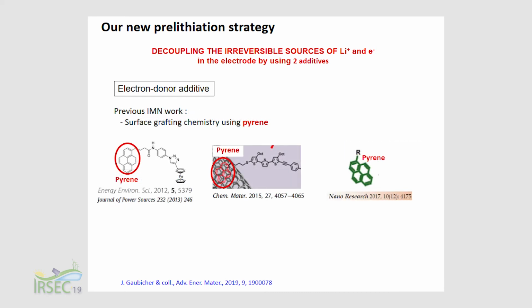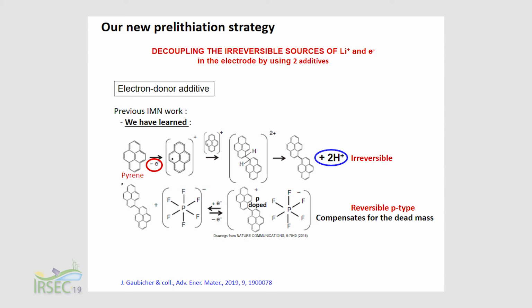So in fact, in our previous work in our lab, a few years ago, we have used pyrene-based molecules to do some surface grafting modification of some materials. And here I show two examples of molecules we have developed. And these works have been published in 4 papers from 2012 to 2017. And from this work, we have learned the following. We have learned that the electropolymerization of the pyrene molecule, of course, provides some electrons irreversibly. This is what we want. And we obtain this kind of oligomer, which can be oxidized with the second reaction shown here, which is a p-type reaction providing additional reversible capacity by uptake or release of anions.